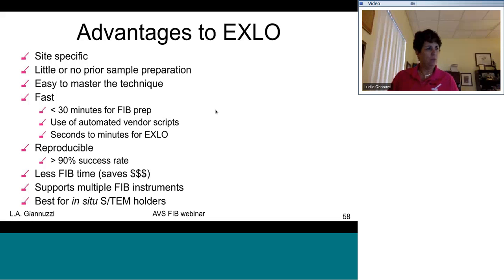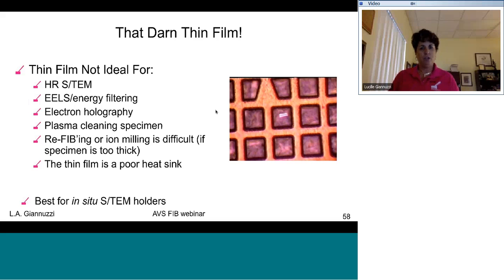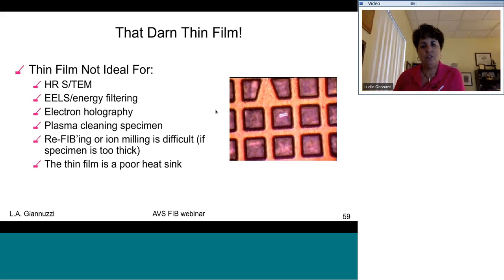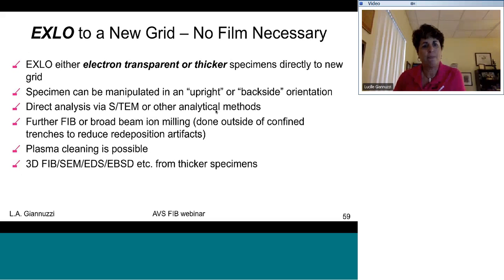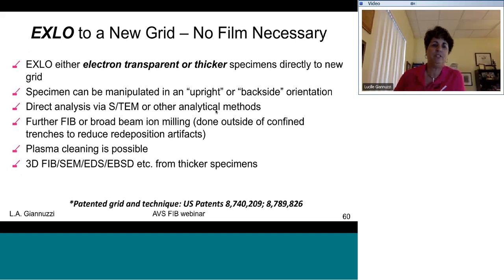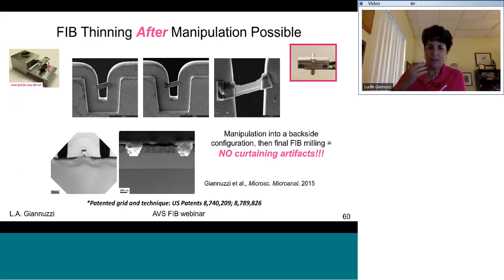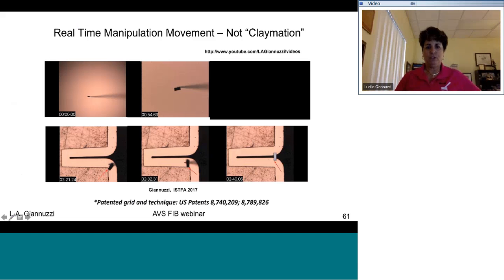etc. What I want to end up with is talk about just a different technique using ex situ lift out without the use or need for a carbon film. And this just gives you flexibility. You can lift out an electron transparent specimen or a thicker specimen directly to a grid. The grid itself forms the support. In this case, you can manipulate it easily into a backside configuration, do your final FIB milling, and you get no curtaining artifacts. So I want to show you how this is done.